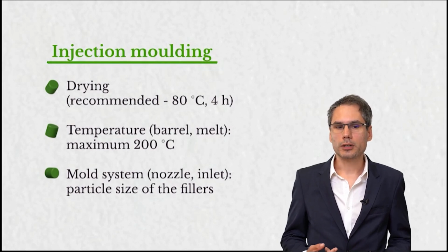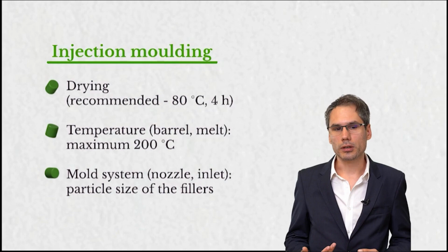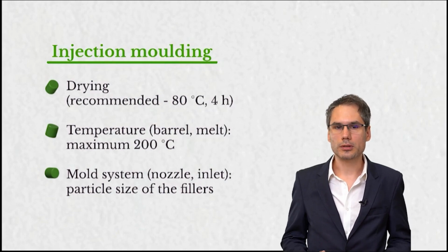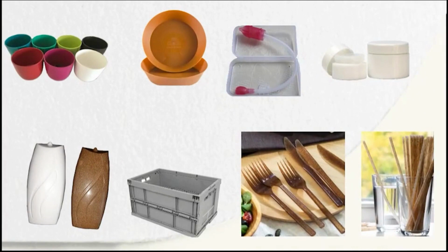In the mold system, the particle size of the fillers has to be lower than the nozzle, of course. You can see the testing parts, mainly from the household appliances industry. We successfully tested many biomaterials for different wall thicknesses, surfaces, and colors, to get more experience of how the material behaves for different injection parameters.